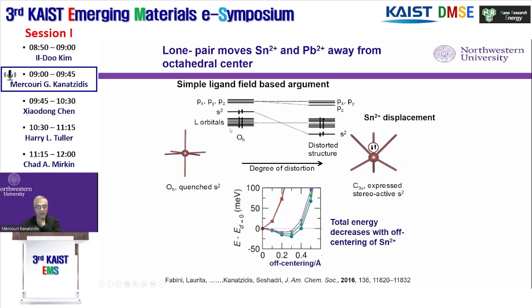On the left, we have a simple MO diagram for an octahedron, where the highest occupied state is the s orbital. That's because you do not allow this s orbital to stabilize, so you destabilize it and make it highest in energy. On the right, we have the distortion where it becomes stabilized and low in energy. And this distortion is more as you raise the temperature. So what happens when you go off-center? This goes down. The other levels are not really affected that much. And so this HOMO-LUMO gap, which is basically the band gap in the semiconductor, becomes wider and wider as you go more and more off-center. When you heat it up to high temperature, it goes more and more off-center. So that explains why the band gap increases with rising temperature.